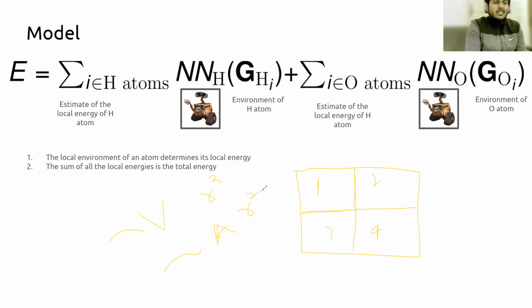And you can say that, in the limit that r tends to infinity, the other way of thinking about it is that you divide it by r cube, and then you take the limit of r tending to infinity, and then you will get the bulk terms, and then you'll get the so-called interaction terms with the 1 over r. For a large enough r, for my thermodynamic analysis, this term will go to 0. So that is more of a thermodynamic argument why energy should be additive, because the components which will give you these bulk terms will be much larger than your surface terms.